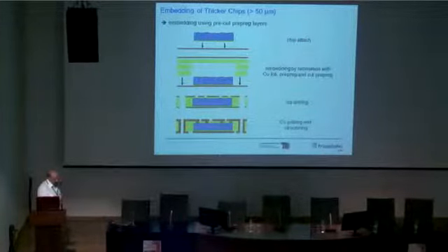The way you do it, alternatively, if you have a thicker component, is to make cavities in your prepregs. So you set your prepregs with a cavity around the component, and then you use a cap prepreg to provide enough volume for the lamination. Again, you follow the same process sequence. You use the UV laser to open the micro vias. You use mechanical drilling to open the through vias, and then you do electroplating. Another interesting feature I would like to mention is that you can open with mechanical drilling even a 50 micron hole. With a laser, the smallest via you can open is about 30 micron.